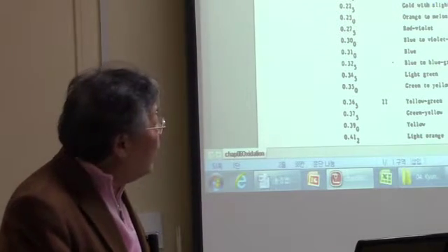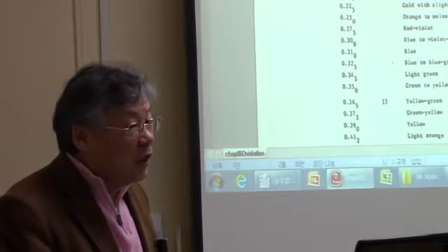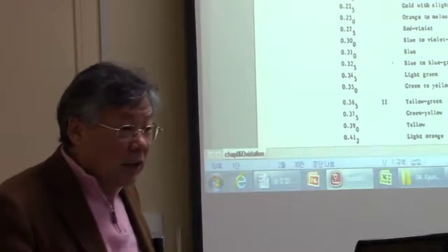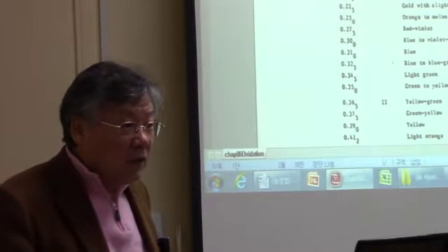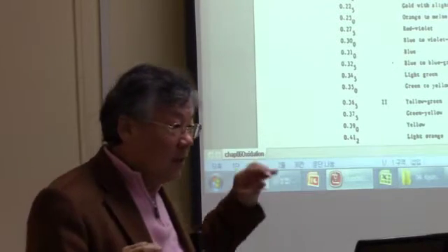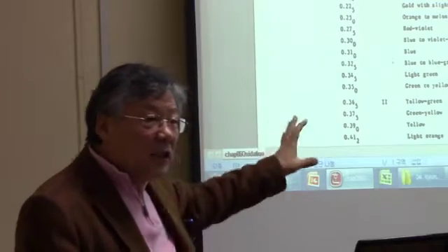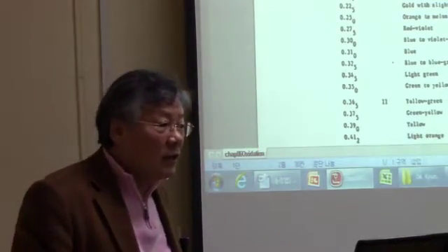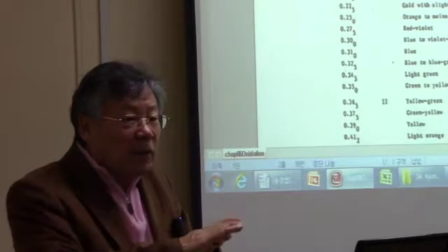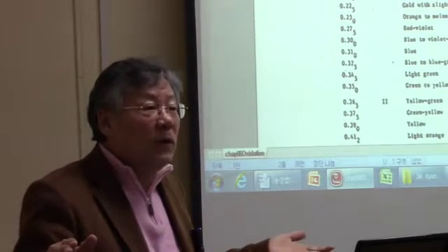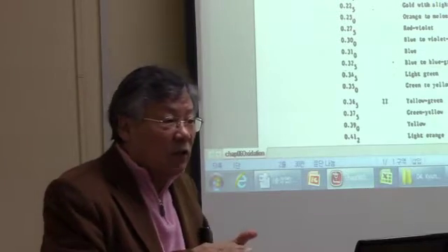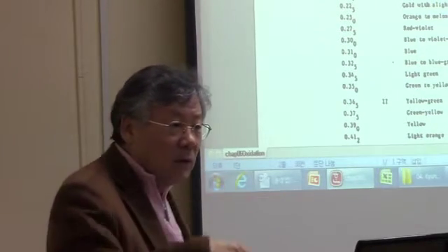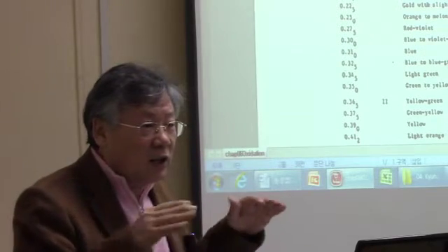So in actual practice, we do not use just this reflective color to identify the thickness of the oxide. But this fact is very useful to find out whether the oxide formed on the silicon is uniform or not. If it is not uniform, you can see the rainbow. You can see the color change.